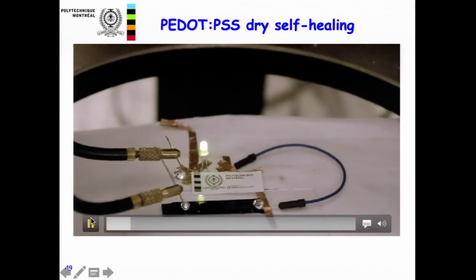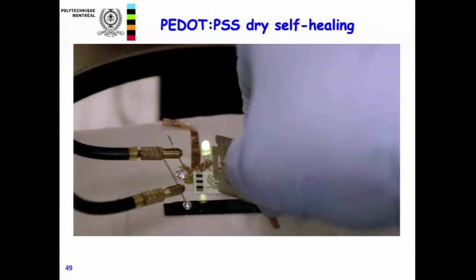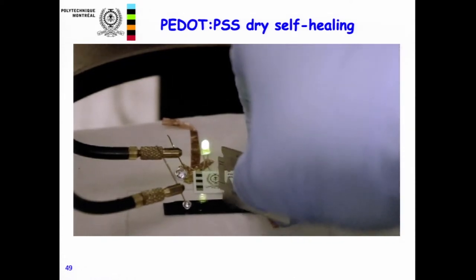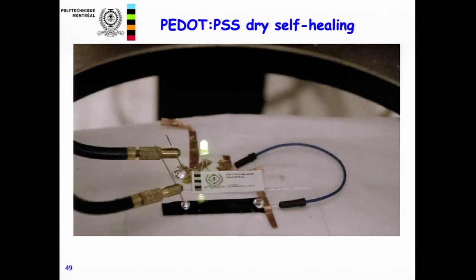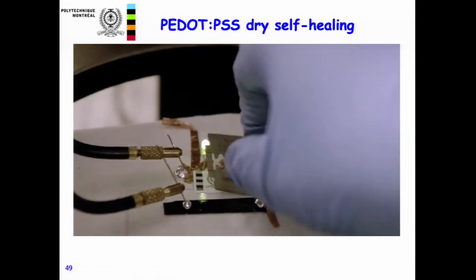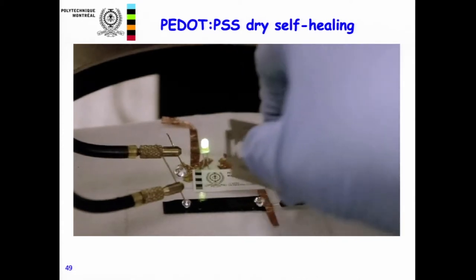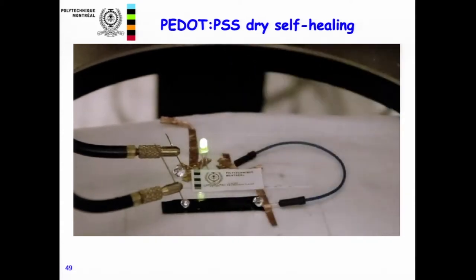This is a dry PEDOT:PSS film. Again, the same setup, and you will see someone cutting. Yes. So you see now we cut the dry film, and we don't observe any change. So it's possible to find appropriate formulations by playing on the mixing of PEDOT, for which you don't need to apply water to have the healing. And this actually could be a very interesting material for some applications where you require self-healing.